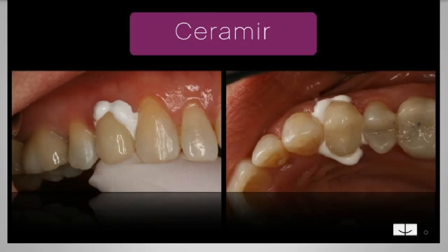Now, with any cement, both resin, dual cured, self-adhesive resin cements, resin-modified glass ionomer cements, bioactive cements, it is super important that when you seat the crown, you do not make adjustments for a good full 4 to 5 minutes, because you have to allow this full chemical cure to happen.